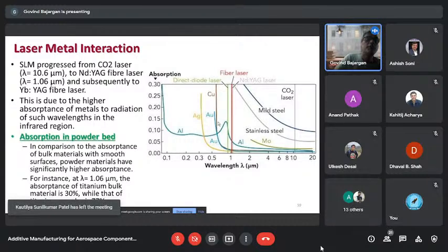So it has been found that as the SLM process started with the CO2 laser, that has a wavelength of 10.6 micron. If you see the figure here, the CO2 laser falls here. If we use a CO2 laser, the solid metal absorption is shown here for mild steel, stainless steel, moly, aluminum. Aluminum, hardly there is any absorption. It's 2%, 3%. Most of the CO2 laser will get reflected from the aluminum. Stainless steel also has around 5% absorption from the solid piece. So when SLM started with this CO2 laser, that was the reason it was not possible to deposit aluminum, because aluminum was not absorbing enough quantity of laser.